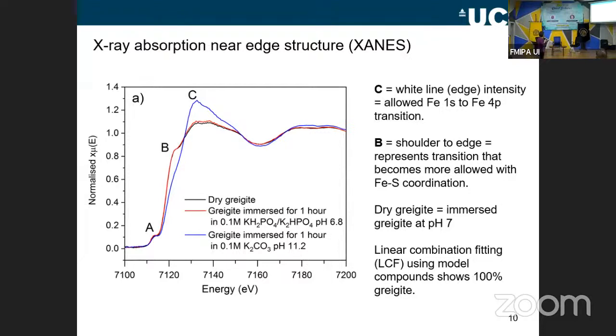So basically looking at the spectrum, what we do is we compare the spectrum to known models, to known compounds. And by doing this, we are able to say that this is 100% greigite. So the black spectrum is the dry greigite, and it matches greigite. And the red spectrum is a greigite that's been left in the solution at pH 6.8 for 1 hour, and it's still greigite. So it's showing that it's stable in the solution. And both of them are showing that this is an iron sulfur material. So ignore the blue spectrum for now. I will come back to that a little bit later and explain it.